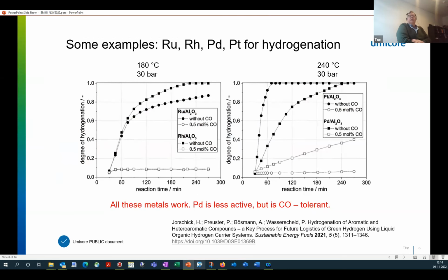These are just some examples showing that you can actually use different catalysts, and this is actually for the hydrogenation. The hydrogenation and dehydrogenation catalysts are essentially the same materials. So for ruthenium and the rhodium, you see at 180 degrees in the left graph, they work quite well. Platinum is actually the most active one, and then palladium in the right graph.